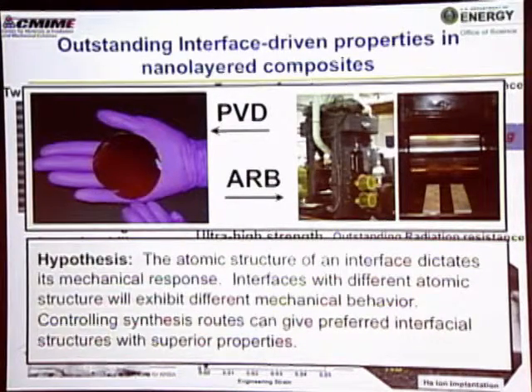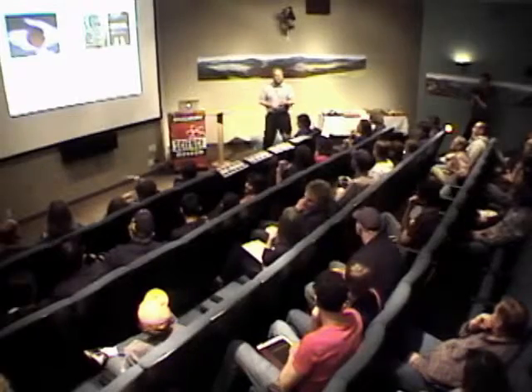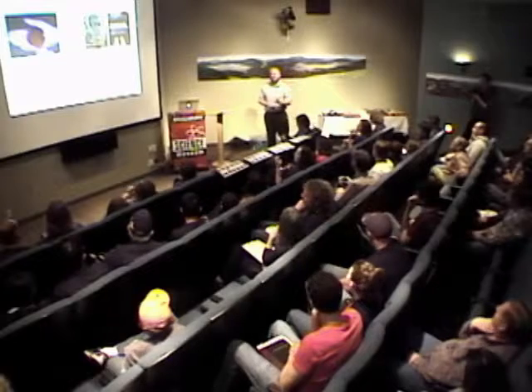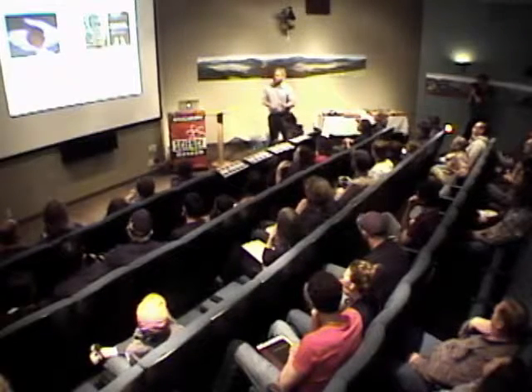So before I move on, I actually brought a chunk of the material that we make by this roll bonding process. This is just a small piece of one of those skis that Tom Nozolek makes. This is 60 nanometers in individual layer thickness, and there are 65,536 layers, give or take a few. So I'll pass this one around as well. But you can see that it's a bulk material. This is something that you can start actually using in a manufacturing type of process.